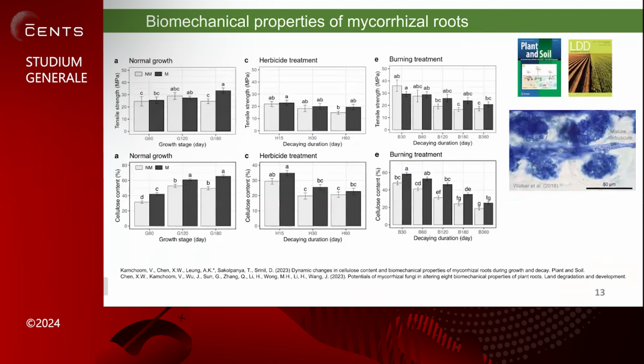In this case, as expected, we can see that the tensile strength of the root improves along the growth period, as you can see in the top left figures. And then once we kill the plant by herbicide, the chemical is put into the plant and the root is killed immediately. In this case, the tensile strength of the root dropped very significantly and very fast. Compared to another approach, where we burn the plant, the root inside the soil decays naturally, and that decay process is much slower. So we can see that the plant can still maintain tensile strength for a longer term, let's say 360 days, before the tensile strength is reduced substantially.